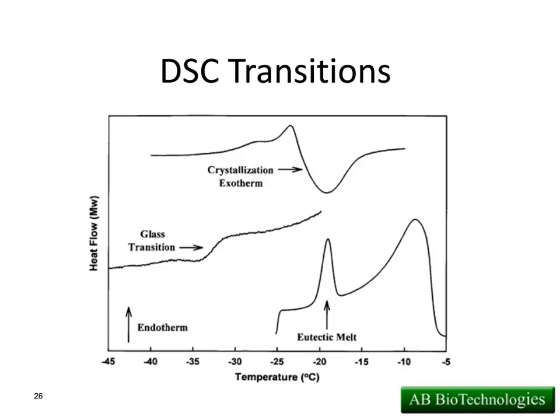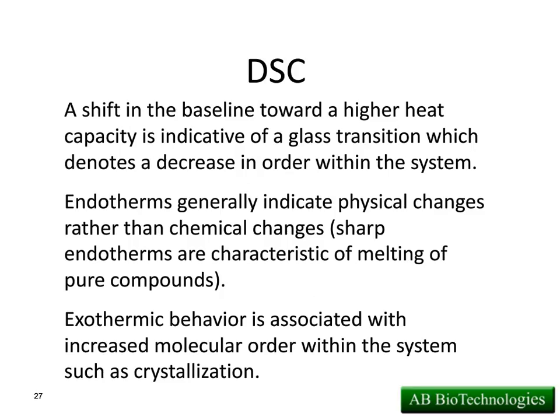Now, on top, what we see is a classic example of a metastable glass. So what we'll see as we're warming up, we see a glass transition followed by a little peak, which is what's called enthalpy recovery, and then we see this big drop. That's crystallization. So that tells me that metastable glass we formed is now crystallizing when we warm it. So this would, again, tell us we need to anneal our sample. We talked about this in DSC, again, how the baseline shifts up or down. Again, if it's an exotherm or an endotherm, those represent different melting or crystallizing, freezing or crystallization events.